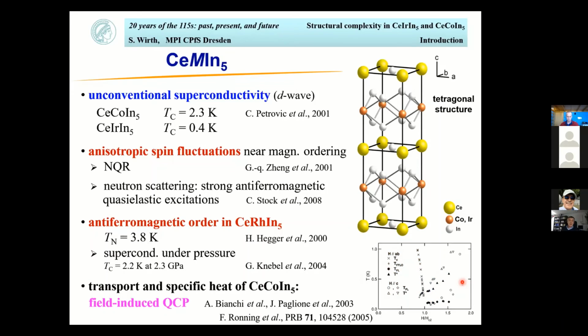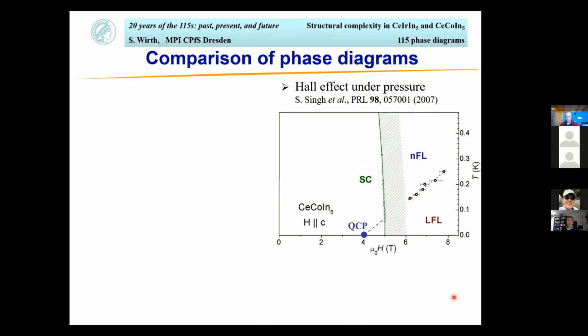Pretty soon after the discovery of superconductivity in the 115s and CeCoIn5, there was also the discussion of a field-induced quantum critical point by Andrea Bianchi or Paglione in 2003, and I've taken here a phase diagram from Philip's paper, and that already shows that there is quite some scatter here in the data. So we thought, okay, let's do some Hall effect measurements to actually line out the crossover from Landau Fermi liquid behavior to the non-Fermi liquid behavior. And if you look at this, then you would extrapolate to a quantum critical point here inside the superconducting dome.